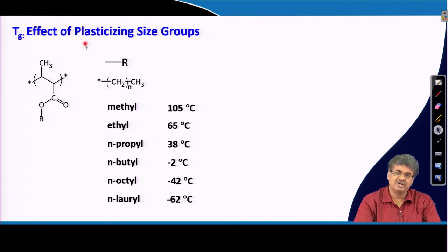Now, this is for the contribution from the free plasticizing groups or increasing the free volume. In this case, in methacrylates, if we increase the size of this R group, this becomes more flexible, and as a result, the free volume increases. And as the free volume increases, the Tg comes down, because, as I explained, when the free volume increases, the polymer has more chance or more space to rearrange itself at a particular temperature. So, the Tg can go down further. If you compare these values, methyl, ethyl, propyl, butyl, you can see as we increase the chain length, the Tg value